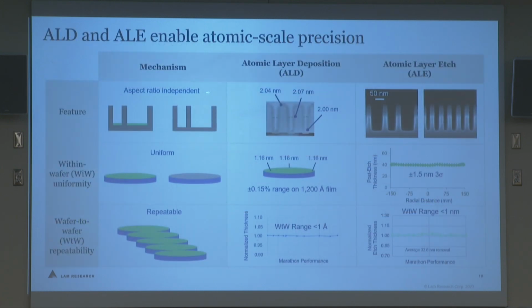So these are examples of what we gain. It's independent of what we call the aspect ratio. If you're etching a feature, how far down is it compared to how wide it is? Aspect ratios of devices can be, at the low end, let's say 2:1, or if you're talking about flash memory, which is a 3D NAND device, those are 100:1. You have to get materials down to the bottom of something that's 100 times as deep as it is wide. That's basically the aspect ratio of the biggest skyscrapers in the world.